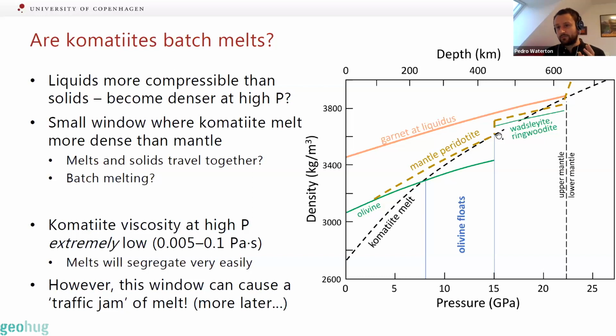So the idea for batch melting was people were suggesting that maybe because the density is so similar, the liquids and solids can essentially travel together and you have continued melting without the liquid segregating and escaping as it would in the shallow mantle. The problem here is that komatiite viscosities at high pressures are insanely low. So about 5 to 100 millipascal seconds. And I think water is about 1 millipascal second. So that gives you an idea of just how runny these are. So this means as soon as you have any small density difference, the melt will segregate very easily and migrate upwards.